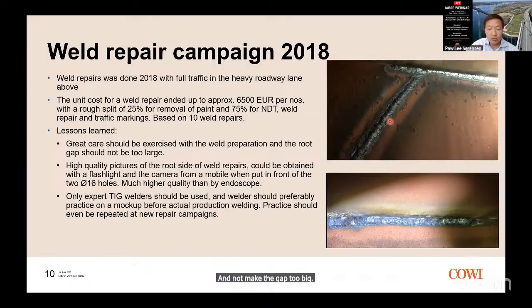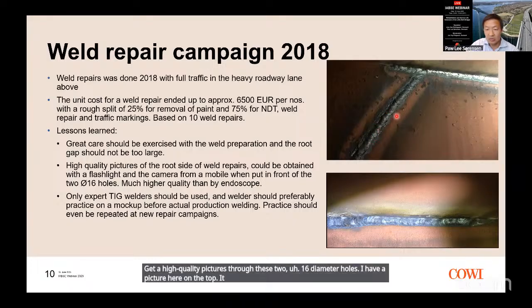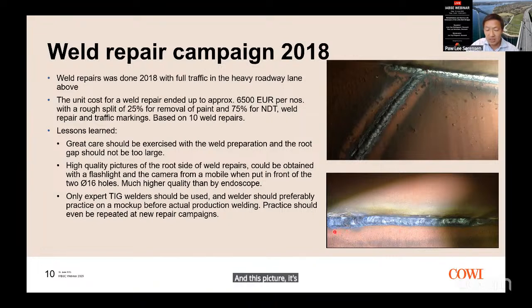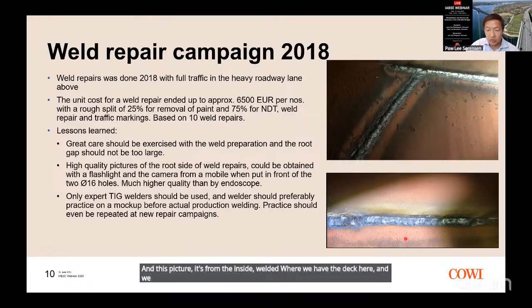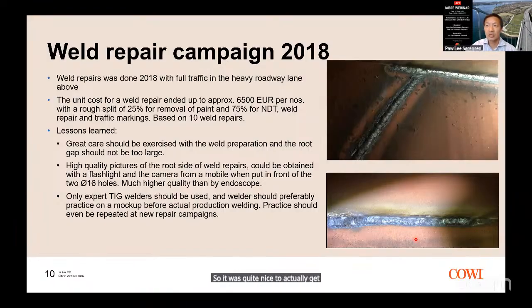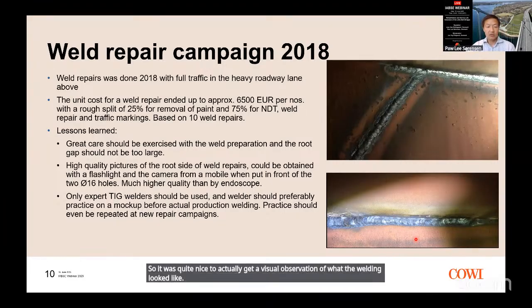Also, we found that we could get high quality pictures through these 16 millimeter diameter holes. I have a picture here on the top. It's from the outside, and this picture is from the inside of the weld, where we have the deck here and we have the trough here. So it was quite nice to actually get a visual observation of what the crack, what the welding looked like from the inside.